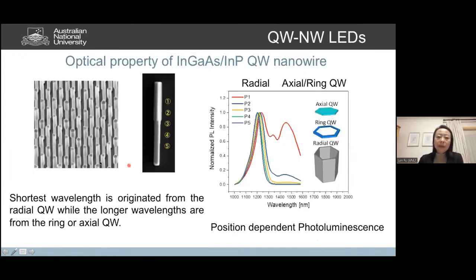So, despite that very strange looking morphology, if you look at the PL, we can actually get quite nice photoluminescence from the nanowires. As I mentioned, if you do the PL along the length of the nanowire, we can see a change of the PL peak. If we put the laser on the top position, we mainly get a strong PL signal from the axial quantum well. When we move down to the bottom of the nanowire, the InP peak reduces and you have mainly very strong emission from the radial quantum well. So that's quite consistent with our TEM results.